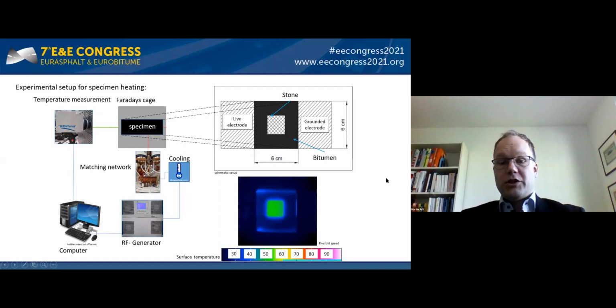So the stone, as shown in the thermal imaging picture in the bottom right corner, will heat up, and the bitumen will follow through heat conduction. This is a very good way to heat up asphalt, as 90% of the mass will heat up and the bitumen will follow just by heat conduction.